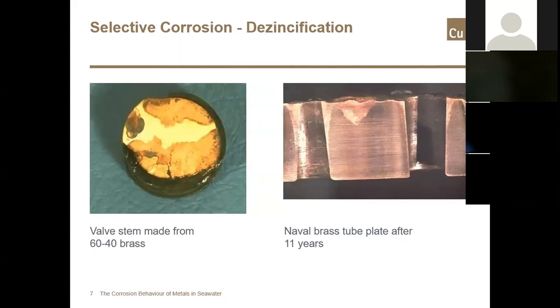However, if you were selecting a copper alloy for seawater use generally, then a corrosion or dezincification inhibitor would be selected, or again, we could look at galvanic corrosion, and we could make allowances that way. The image on the right shows a naval brass tube plate that's been in service for 11 years. This was specifically over-engineered, and you can see actual corrosion on the surface of the material. But because it was over-engineered, there's been no problem with that particular component, and the component was designed correctly.